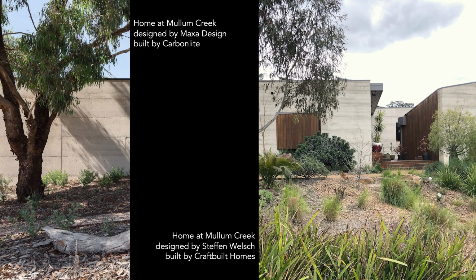Initial resistance to SCMs really subsided on that project as the concreters found that ground slabs containing SCMs were stronger and with less shrinkage cracking. And as the bricklayers realised that bagged cement containing 50% SCM was equivalent to general purpose Portland cement in availability, performance and price for the mortar they were mixing. And the rammed earth contractors found that slag, so that waste from steel smelting, performs quite well as a cementitious material without reducing those nice earthy wall colours to a drab grey.